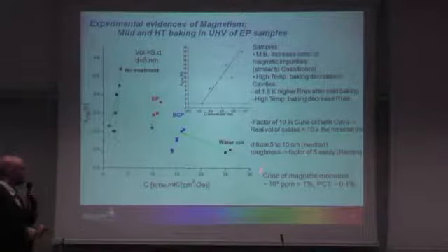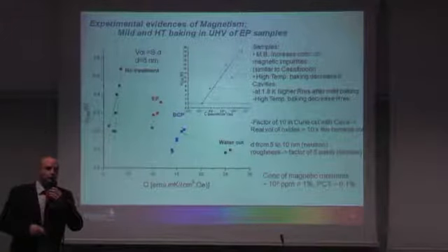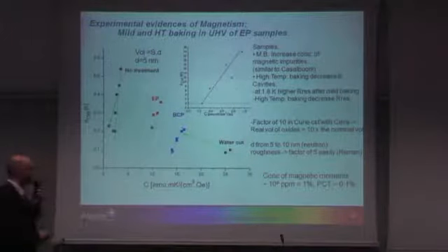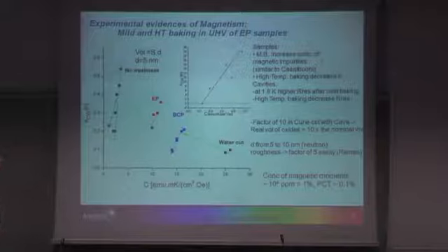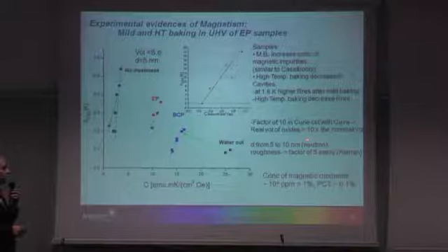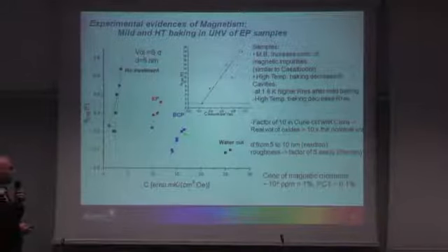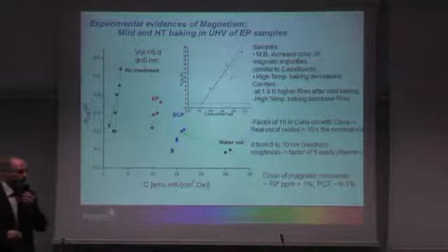So I guess it depends very much on the technique you are using when you want to calculate the thickness of the oxide. I know XPS shows more or less 3 to 5 nanometer too. So this is still a mystery. But it might be that the thickness is thicker than what we actually think it is.